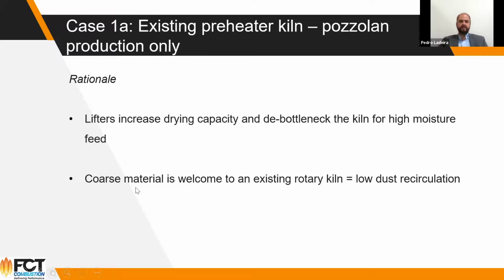So the other thing is that the coarse material is very welcome for an existing rotary kiln. So we're going to have low dust recirculation. So when the feedstock is not prone for dust generation, you can use higher velocity and profit from higher kiln capacity in the end of the line.